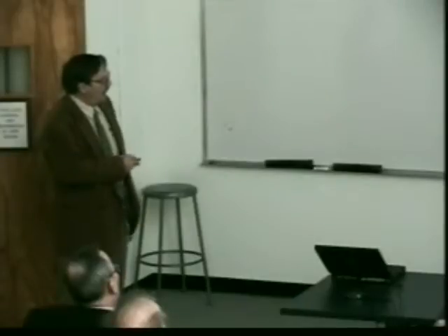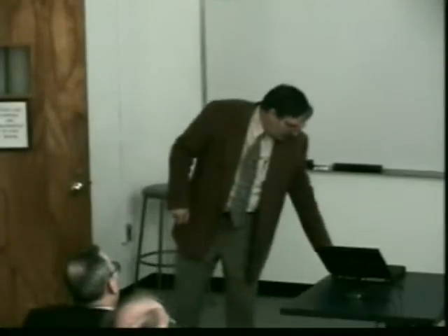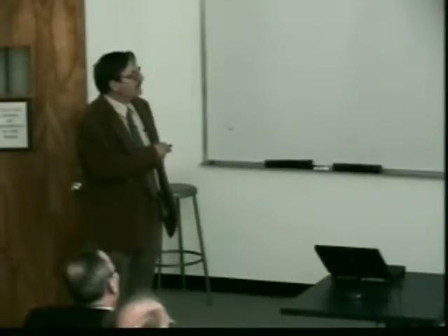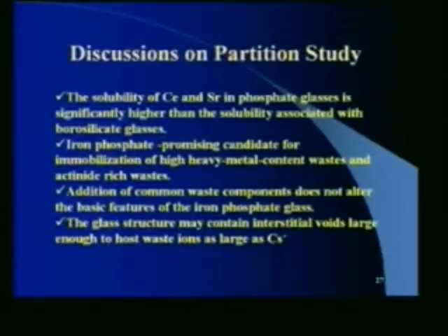Similar thing for cesium. This is again 2% weight loss from the glass phase at about 12 or 13% loading into the system. So this is an example of a vitrification study where we found that the solubility of cesium and strontium in phosphate glass is significantly higher than in borosilicate. These are promising candidates for immobilization. The addition of these components doesn't appear to alter the basic features, and the glass structure may contain interstitial voids which are large enough to host these larger atoms.